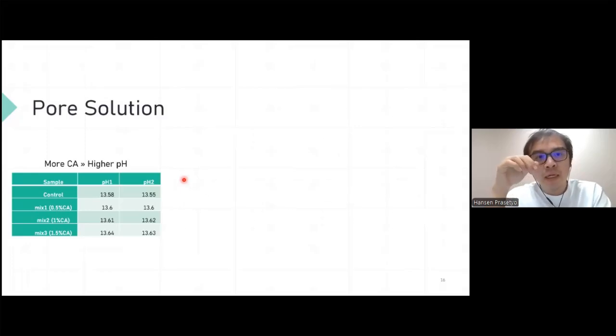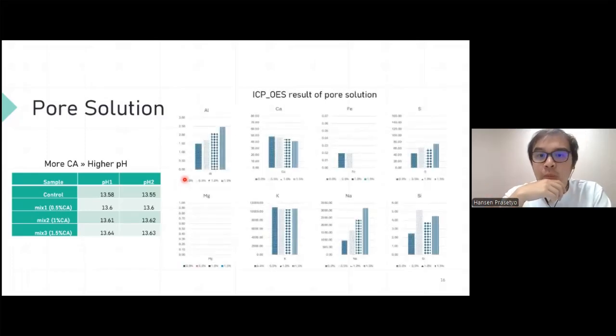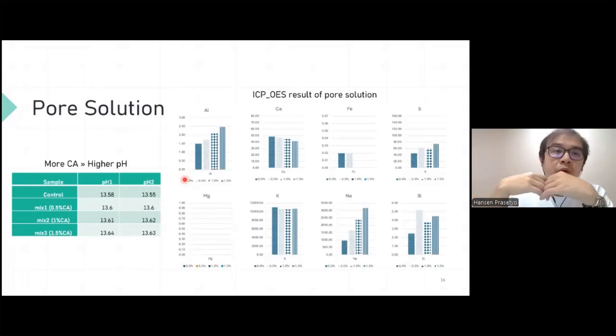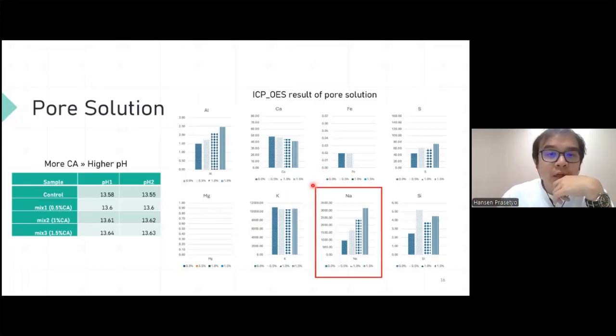I also did ICP-OES on the pore solution as well. I just wanted to see what ions are in there. And from this result, I think the most interesting one is sodium. In the pore solution of my samples, I see an increase in sodium when we increase the dosage of crystalline admixtures. The other ions don't really show such a clear result. So we might have to think about what it means if there's a lot of sodium in our pore solution.